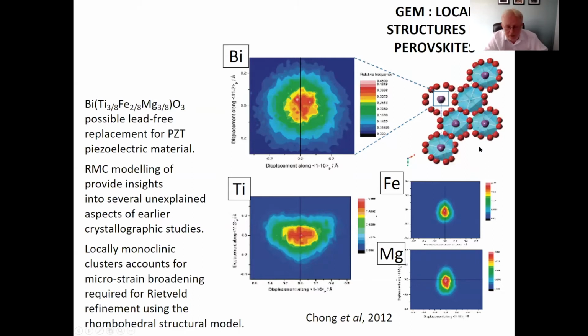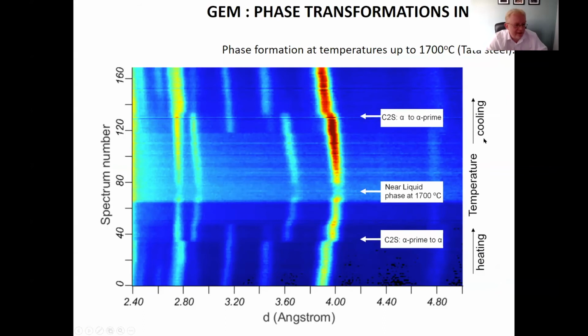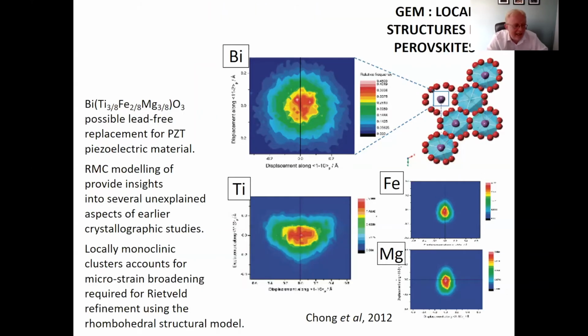We can do things on the local structure and on the average structure as well. So the previous experiment, this is looking at the average structure, is looking at all of the diffraction from all of the sample in one go. We can do something called a pair distribution function, where we analyze the local structure around each of the atoms within the material. And if you look at this, these are looking at essentially the thermal motion of these atoms of this material. And you can see the motion of the bismuth atom is very symmetric, whereas that titanium is spread out across the X, and the iron and the magnesium are spread out across the Y. And these local deviations in the properties of these cations are what give this material its piezoelectric properties. So this anisotropic displacement of these atoms allow you to understand the origin of the functional properties of this material through a very high resolution powder diffraction experiment. And we do studies like this quite a lot as well.